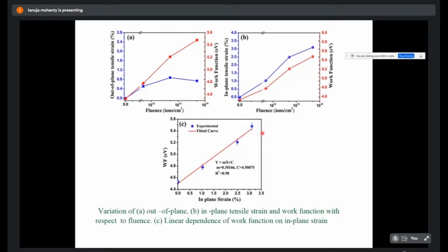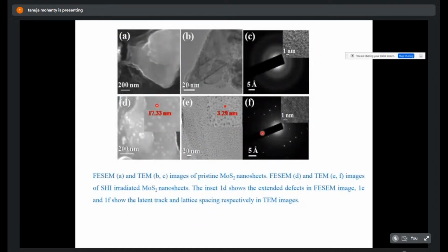So Raman spectroscopy gives you the optical properties, and the electronic properties are the surface electronic properties, because the work function is measured from the surface, and they are linearly proportional. And also we find from TEM studies that there are tracks created in these materials, and the defects which are produced can be seen. These are materials which are initially pristine, and then there can be tracks produced in these materials.